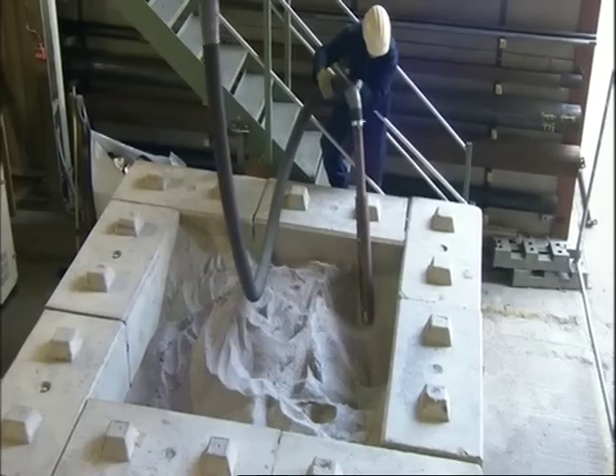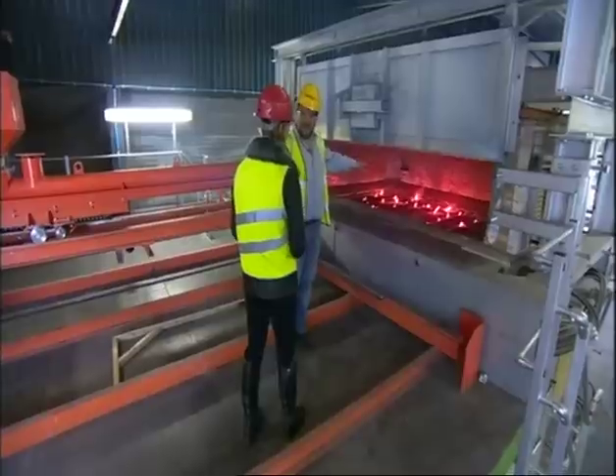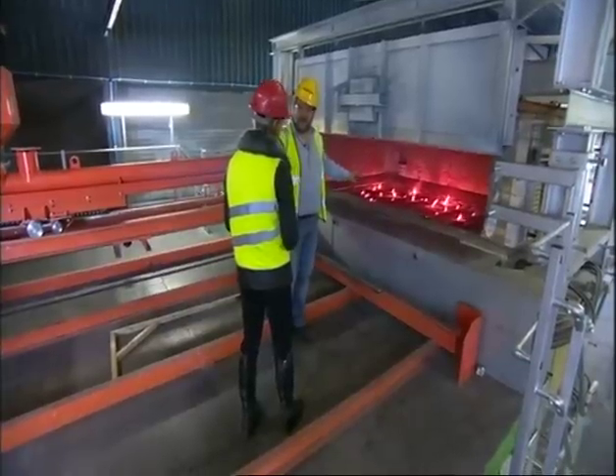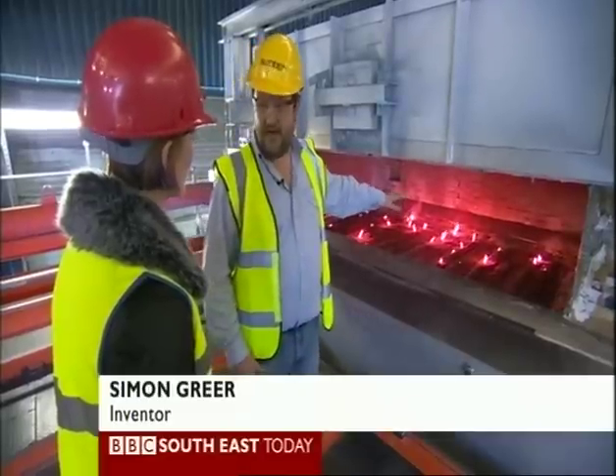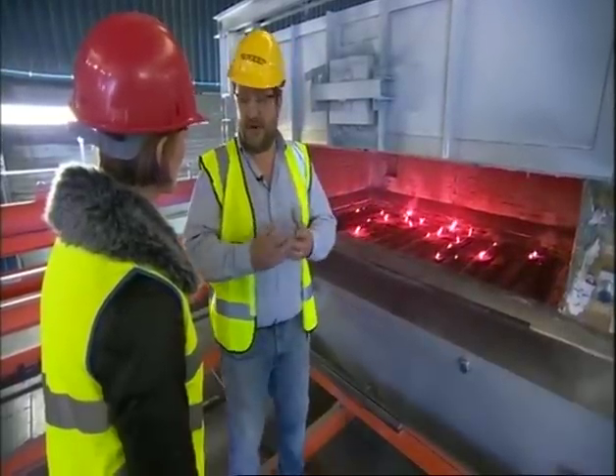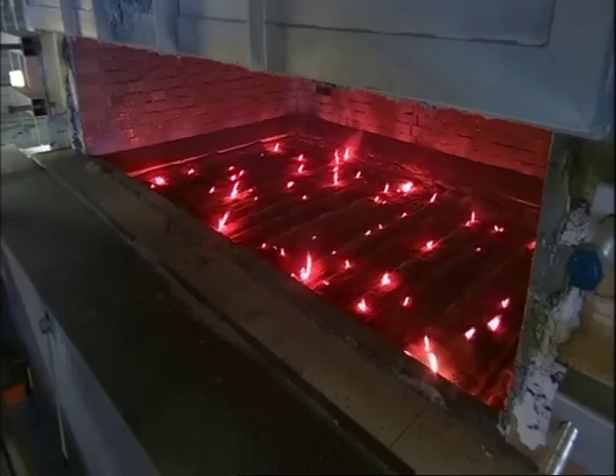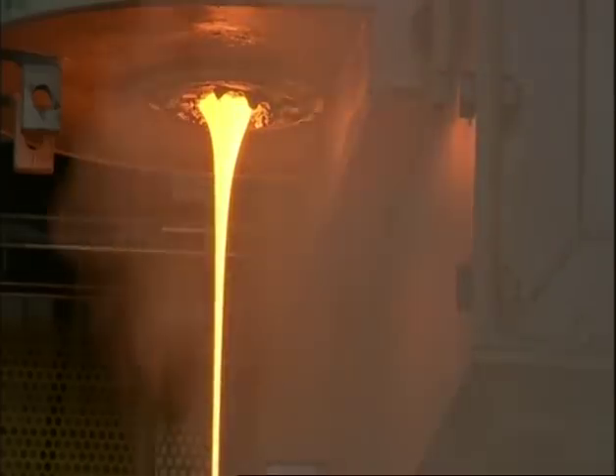It's sucked into a unique furnace. This is the heart of where the glass starts its journey, and it's delivered onto a pot of 18 tons of molten glass, which is underneath that dark blanket there. It's over 1,000 degrees, and at that temperature we can chemically separate the lead from the glass and simply get the lead to fall to the bottom of the furnace and let the glass continue on its journey.